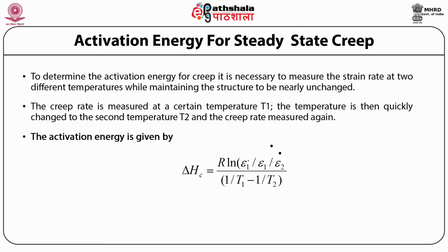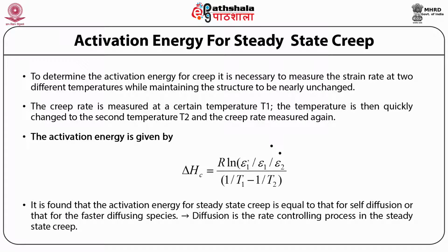So it is observed that the activation energy for creep is equal to that for self-diffusion for pure metals, and that for the solute in dilute alloys, which implies that the diffusion is the rate controlling process in the steady state creep.